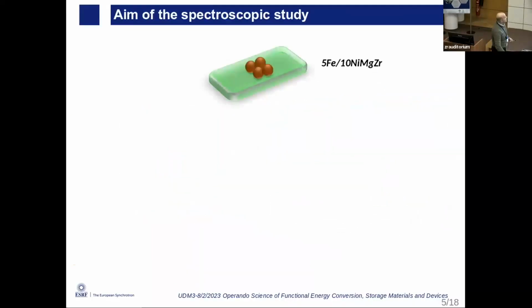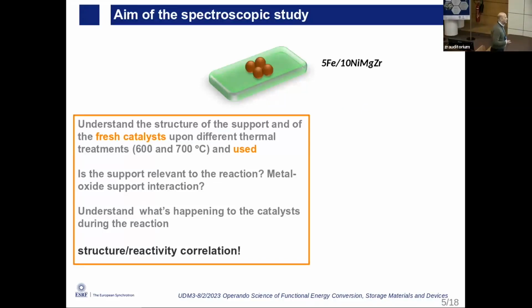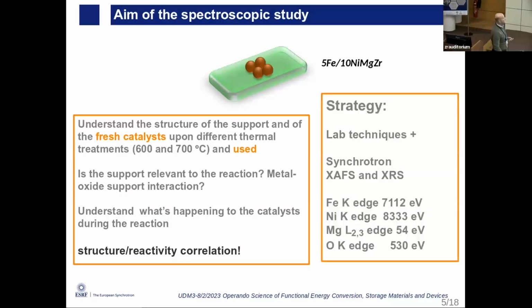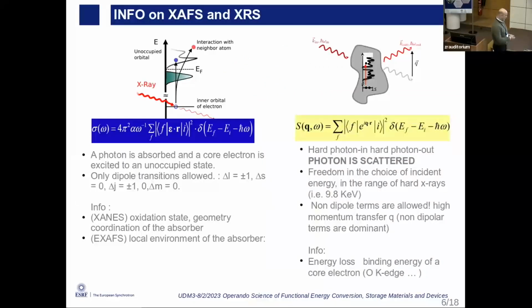So the idea, of course, is that typical laboratory techniques like diffraction and XPS are not fully conclusive to understand what's happening in terms of metal oxide surface interaction. So to establish a better structure-reactivity correlation, more advanced techniques are necessary. And of course, the idea was to use the synchrotron-based ones, so X-ray absorption spectroscopy and X-ray Raman spectroscopy. So then to resolve selectively the site, and to look more closely at what's happening to the different atoms, so the iron, nickel, magnesium, and oxygen. For the iron and nickel, of course, XAS is a good technique. For the low Z elements, XRS seems to be the best. Concerning the Raman, the advantage is that we can use a high energy hard X-ray.